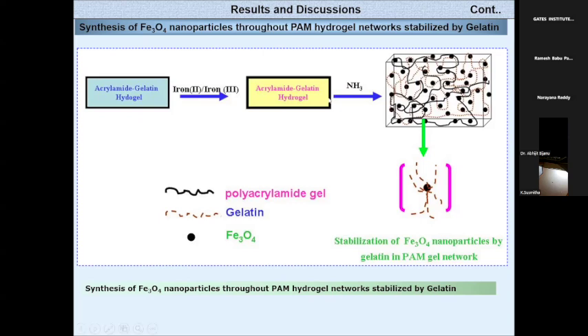In this way, you are seeing this hydrogel network. It is a copolymer system, and the black particles, the black dots that I indicated, are Fe3O4, which is one type of iron nanoparticle. What is happening here? The Fe3O4 iron nanoparticles form, and simultaneously they are entrapped by your polymer network, so that it will maintain good stabilization and will not go for any agglomeration, so that you can get the stability of the reaction. This is the way we developed the acrylamide gels and hydrogels. Simultaneously, you are getting these hydrogel magnetic nanocomposites.